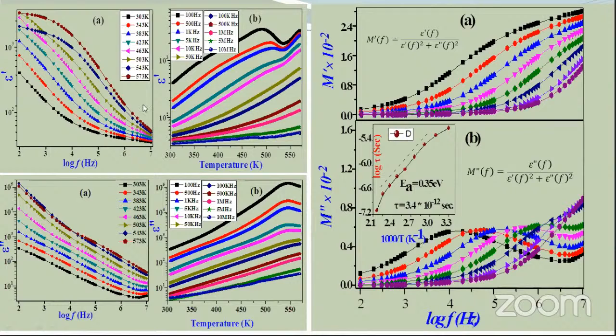The same data can be presented in this form. In this form, the modulus value increases with increase in frequency. At low frequency, it reaches 0, and at higher frequency, it reaches its asymptotic value. This property indicates there is negligible contribution of electrode polarization in the modulus representation. And in the middle of this frequency range, we get the dispersion. This indicates the conductivity relaxation here.